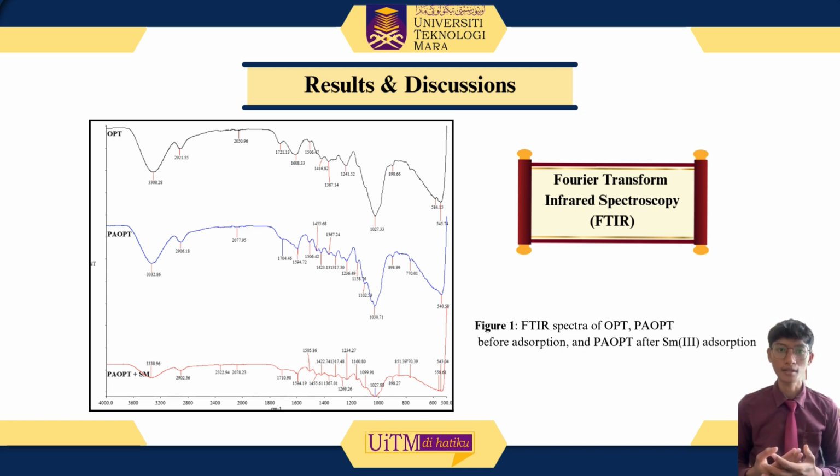The peak at 1608.33 corresponds to the C=C bonds in the aromatic ring, cellulose and lignin. The bands ranging from 3040 to 3600 show alterations that are most likely caused by the complexation of samarium ions with free hydroxyl groups, specifically from the OH group.